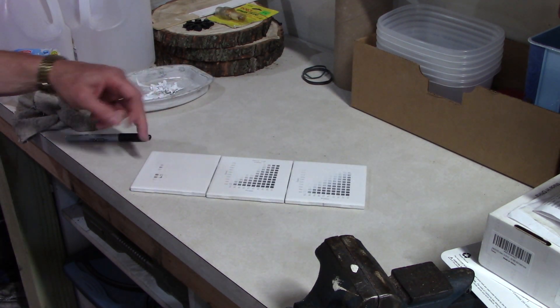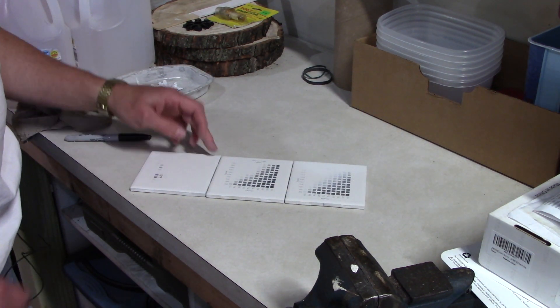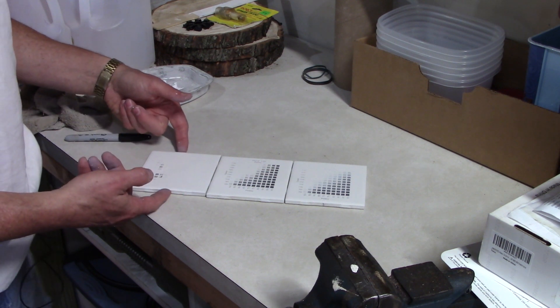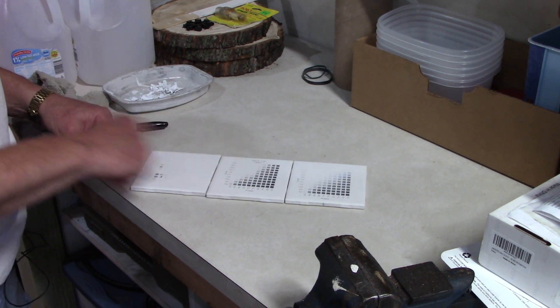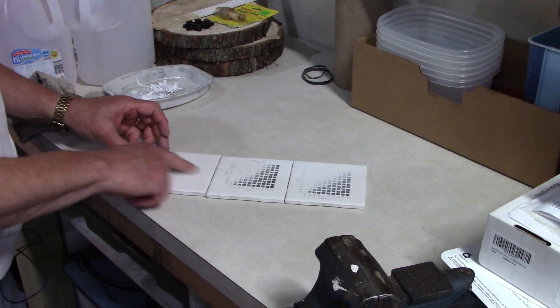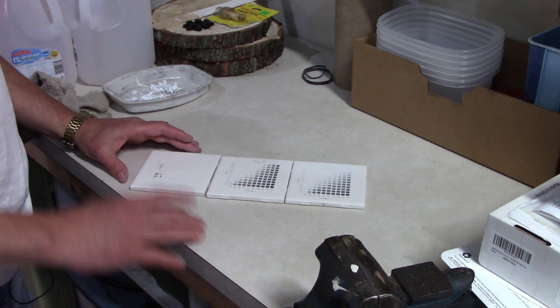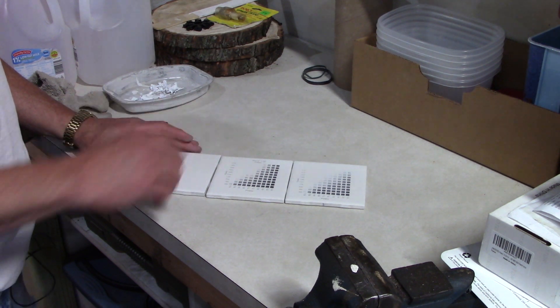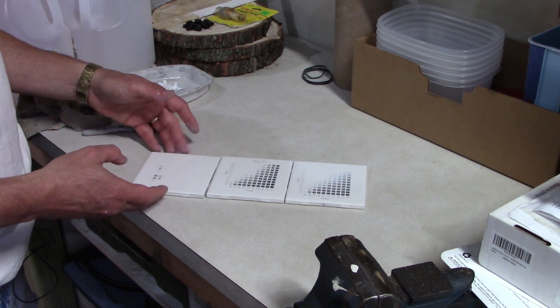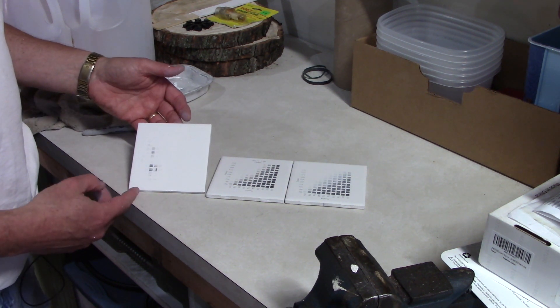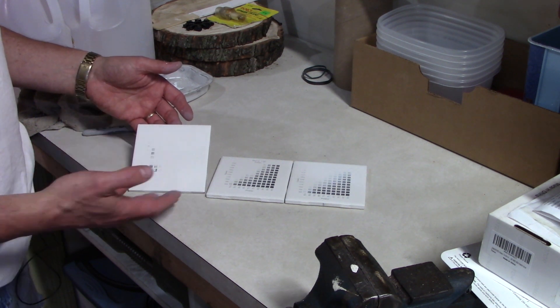So kind of the thing you need to do, this is too much paint. Obviously nothing really stuck. It didn't work real well. This was two nice coats, one horizontally, one vertically across the tile with the can a little bit closer. So there's much more paint getting on here. And the results speak for themselves. Too much paint didn't do much.